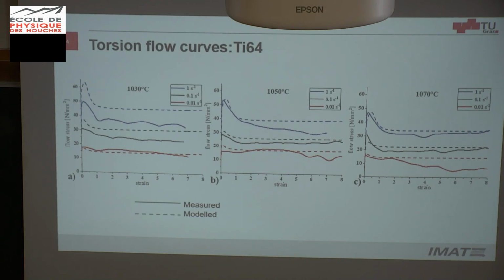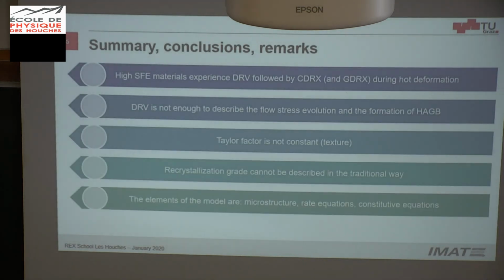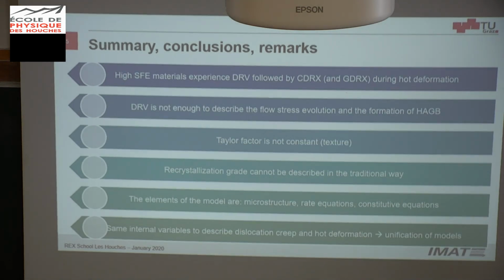Okay, I'm very sorry that I was that slow, but what I want to summarize is that we are dealing with high stacking fault energy materials. They go into dynamic recovery, followed by continuous dynamic recrystallization, but geometric dynamic recrystallization can also occur. We have texture changes, we have grain refinement at very large strains, and we can model it. The model allows us to explain both the stress behavior as well as the microstructure behavior. So if you have any questions, I will be glad to answer them.